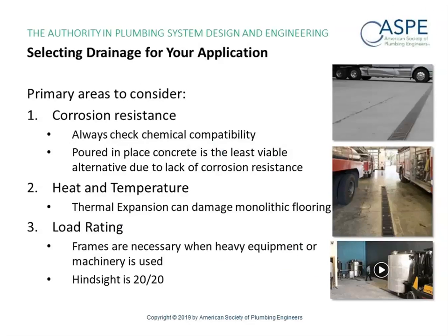There was a guy from another company that actually pointed this out to us, and he was talking about the granular structure of stainless steel. And he said it's like when you used to go on a road trip and you would put a push pin into the map, and then you would connect the push pin with a piece of yarn or thread or whatever to kind of show your path. And that's how the granular structure of stainless steel is. And what chlorides do is they get deep into that granular structure, and then they follow that roadmap and they tear the pipe to shreds. So always check your chemical compatibility.